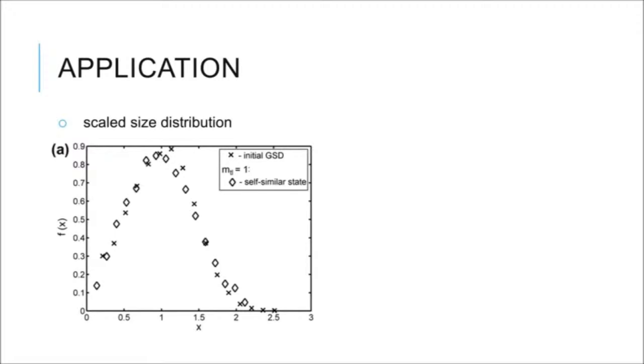Here, the crosses show our initial grain size distribution, and we see the self-similar state for normal grain growth, where all triple and quadruple junctions have the same mobility as the grain boundaries. It's quite a nice unimodal distribution, somewhere between 0 and about 2.1 or 2.2, meaning the largest grains observed are 2.2 times the average grain size. The distribution has a maximum roughly around x equal to 1.